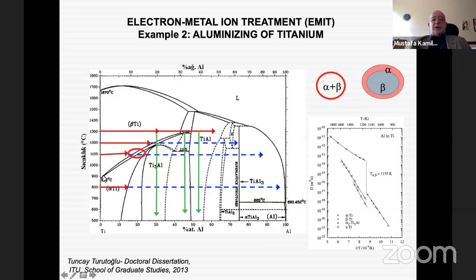So when we go to a temperature beyond the alpha beta transition, the diffusion process takes place very fast until we reach this region. That's what we have observed. When we come to this region, around the beta particles, alpha phase starts to form that limits the diffusion again. So we again switch to the aluminum-rich region because of the continuous deposition of aluminum on the surface of the material. Our diffusion couple changes from diffusion of aluminum into titanium to diffusion of titanium into aluminum. So this is a switching of the diffusion couple by coming to a region where alpha is present.